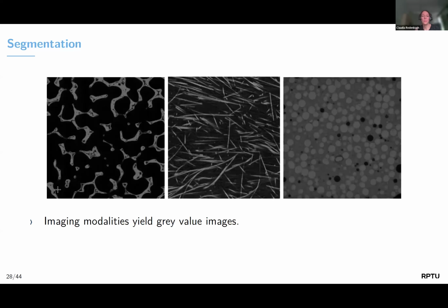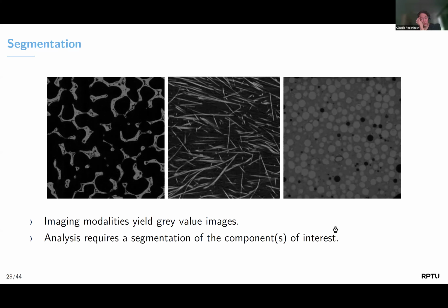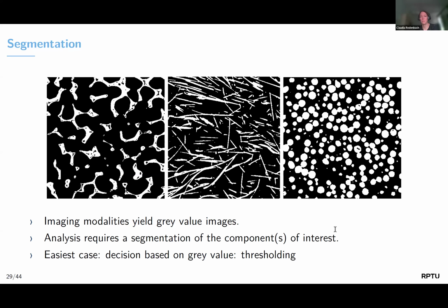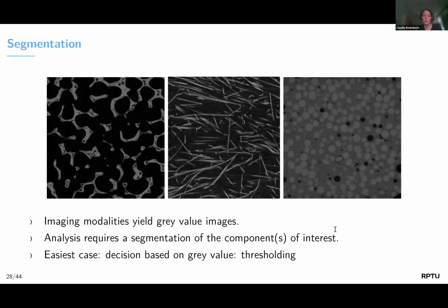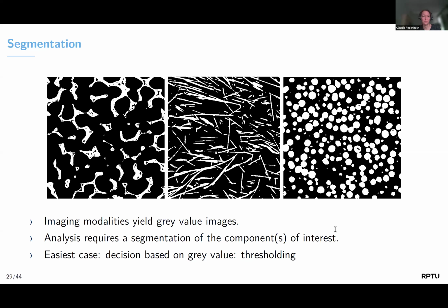So here are some examples. So you have gray value images. In this case, it's CT scans. And for instance, here we see the strut system of a foam. Here we see a fiber system. Here we see some grains. And if we want to analyze them, we have to distinguish them from the pore space or from the matrix. Ideally, and that's possible here, this can be done by simple thresholding, meaning you just set a threshold and say everything that is brighter than a certain value is the component of interest. So here you clearly see this is easily possible.